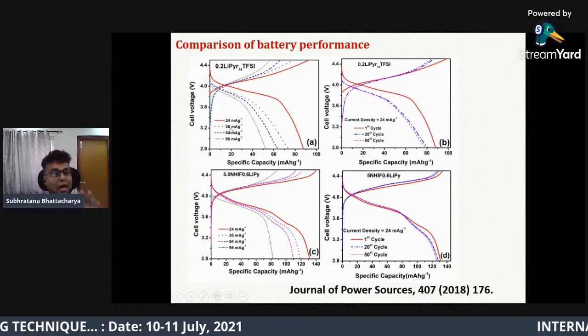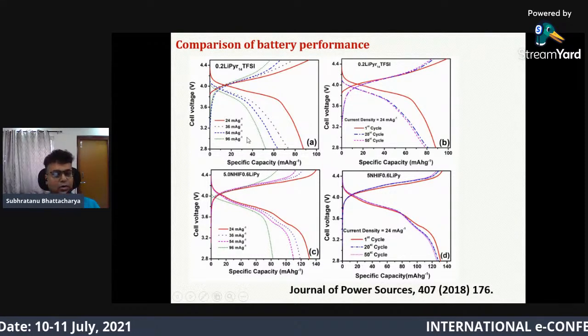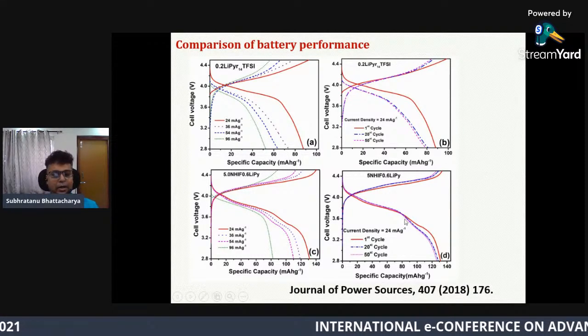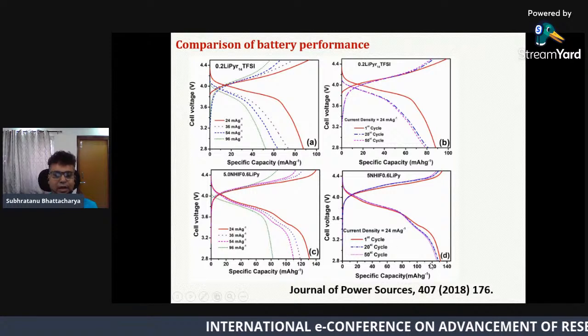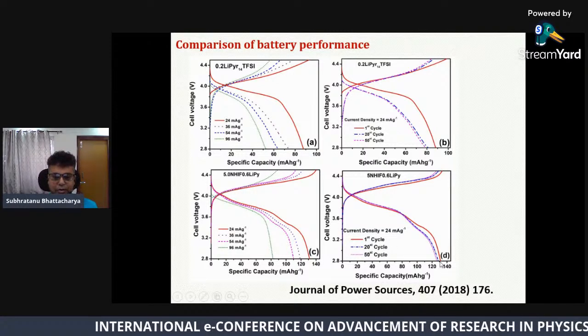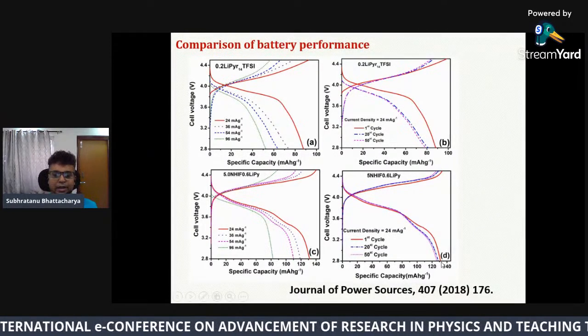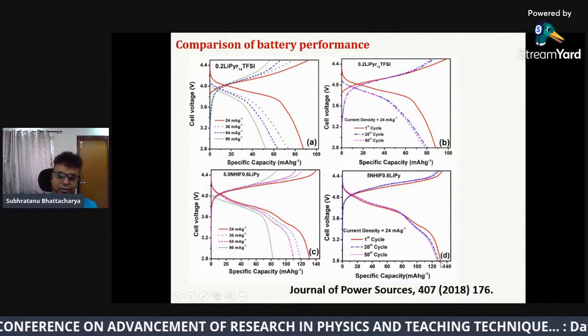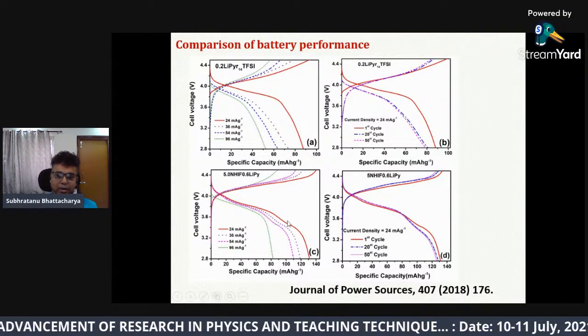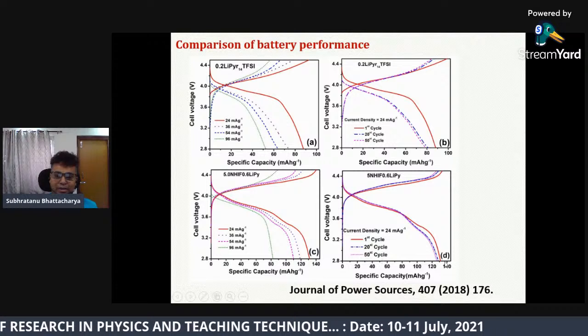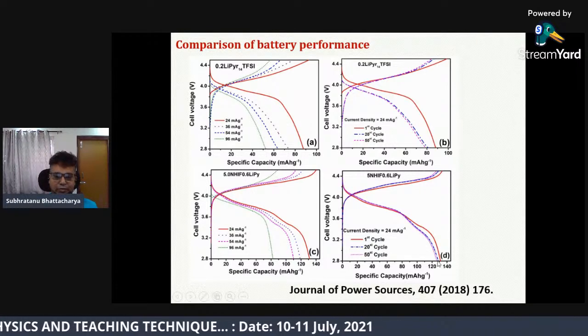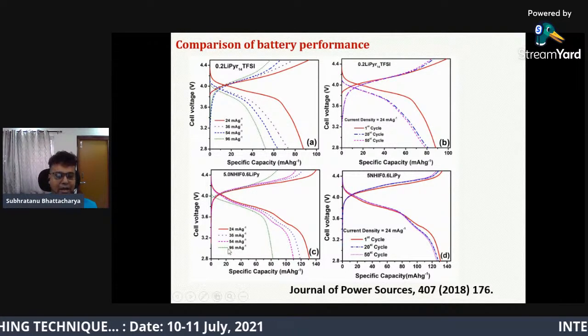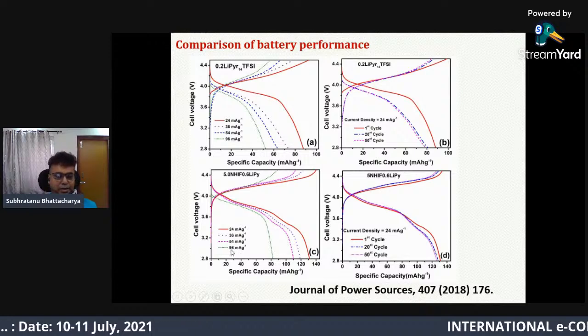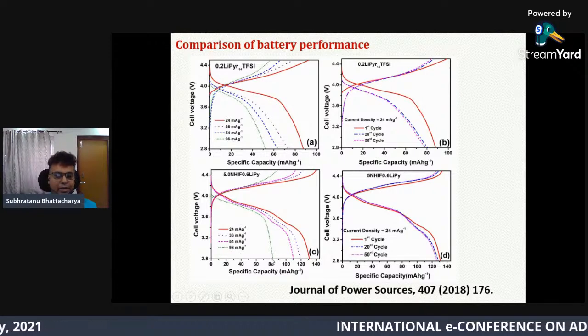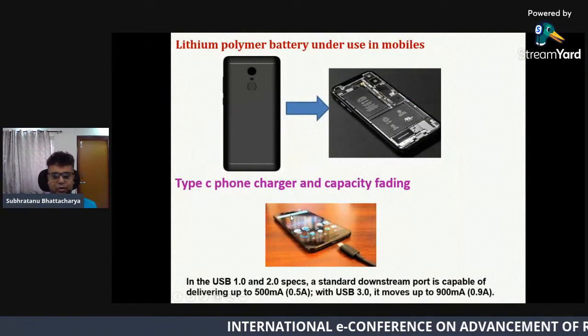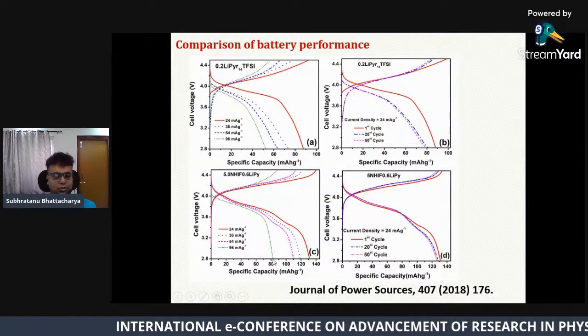with substantially high current. I don't know if you can understand it or not, but in our case, you can see we have achieved nearly the theoretical specific capacity in the first cycle, and even at 50 cycles there is very little capacity fading. And at a substantially high current density, we have achieved up to 80 mAh,